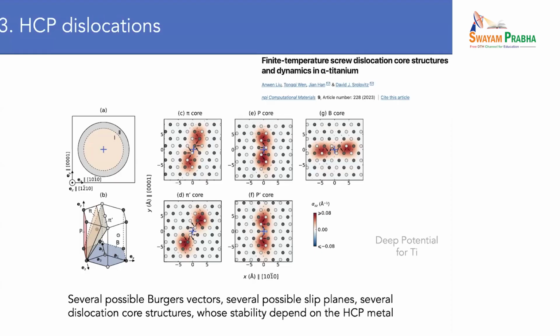Now, in the basal plane, as well as in the prismatic plane here, there is a stacking fault. And so there is a dissociation. It's not the same as here, because here the A Burgers vector dissociates into A over 2 plus A over 2. They move away and they leave in between a stacking fault. But it's of a rather high energy, so the dissociation is always quite small, right? And then you have more complex core structures that involve nanotwinning in these other planes. Sorry, this one is the prismatic.